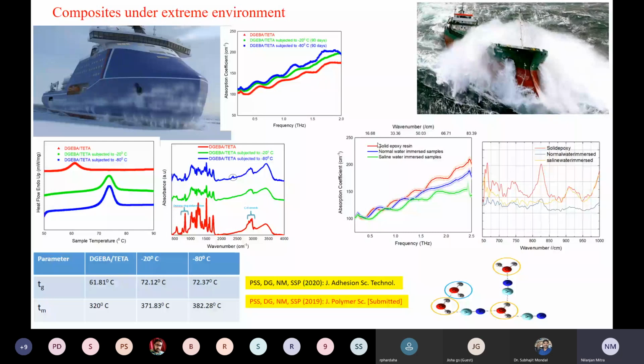So in those situations, you are placing your polymeric material, or whatever material you have on the ship, in those extreme environments for quite a long time. Now, we know that there is no degradation in metallic materials as such, but obviously they're heavy. On the other hand, polymeric materials are lightweight, but they do degrade under extreme conditions. So what we were probing is, let's say I have a glass fiber composite, and I keep it under extreme weather conditions like -20, -30 for an extended period of time, and then see if there is any degradation in the material. That's what we were doing here.